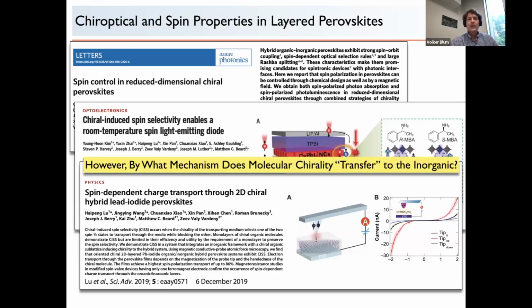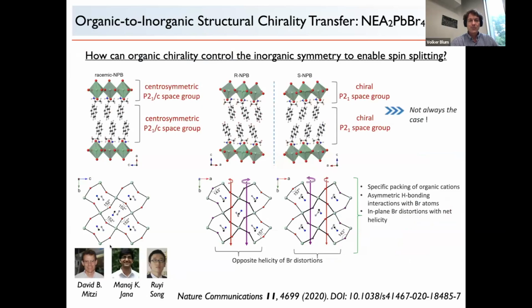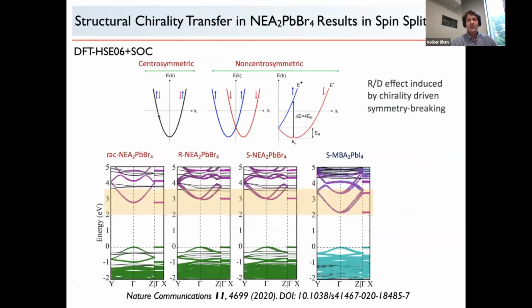And we can look at the chirality. We can go to our colleagues here, our experimental colleagues, David Mitzi, Manoj Jana, Ruyi Song did calculations. They did X-ray diffraction. They looked at hydrogen bonds, and they showed in detail how inversion symmetry breaking is conveyed to the inorganic layer. And in short, we can calculate energy band structures.